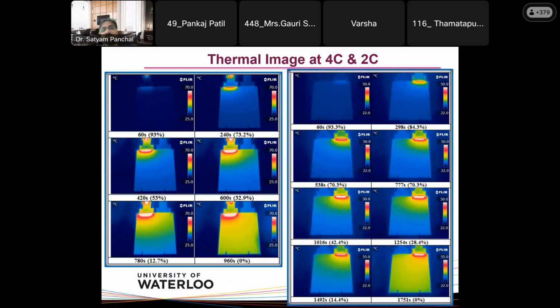After that, thermal images were taken at different C rates: 4C as well as 2C and 3C. And here you can see the blue image at the beginning of the discharge, a little yellow in the middle of the discharge, and then this is the end of the discharge. Again, I have several images, around 2000 images. So if you are working in the thermal area, and if you need any of these images or any data, feel free to contact me, and I will be happy to provide all data from the University of Waterloo.